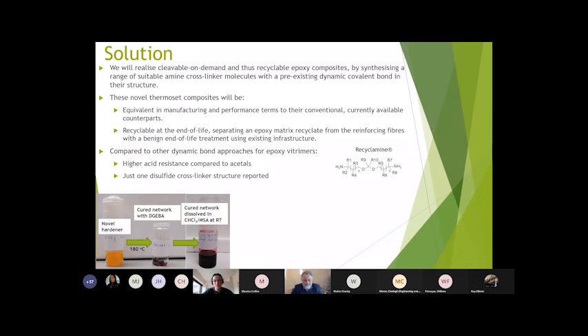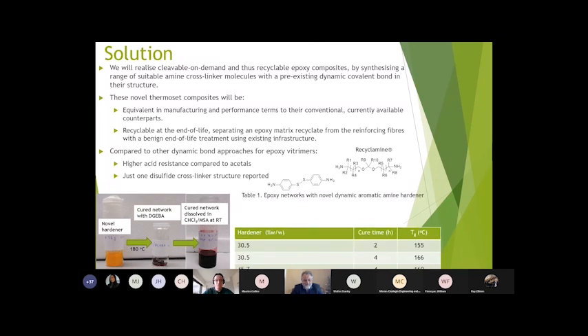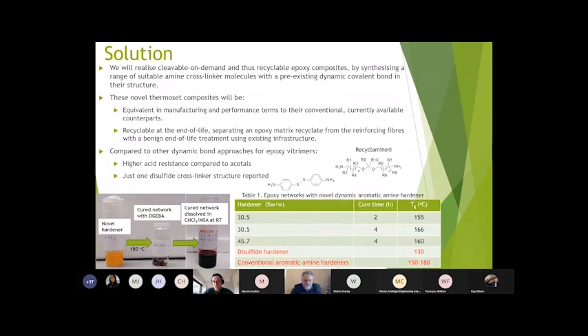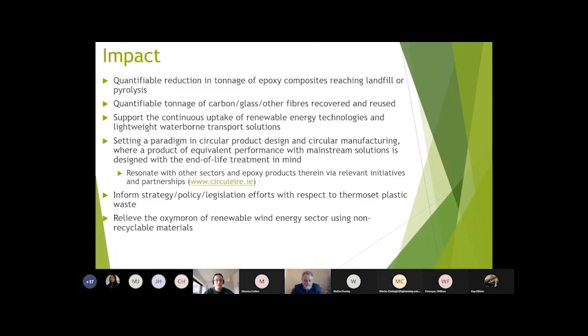And of course, there is just one disulfide cross-linker that has been reported and has been used also in the project that the area composites are part of. Just to finish off with a little bit of data for you, we can use our novel hardeners. They can be combined with the epoxy, and we can use different formulations and curing times. And as you see from the table and the Tg values there, we can actually be very much competitive and on equal terms with both the conventional networks coming from standard aromatic hardeners as well as with the disulfide one. So we feel that we do have a good proof of concept with respect to equivalence in manufacturing as well as performance terms at this stage.